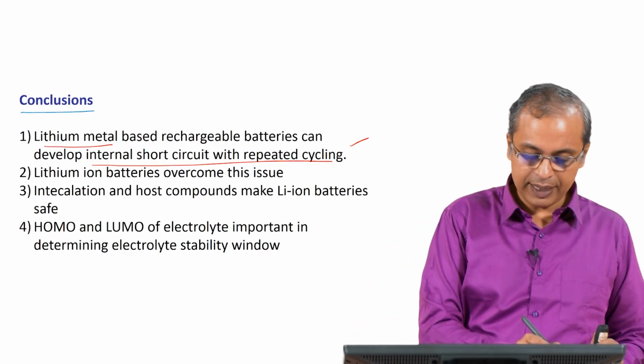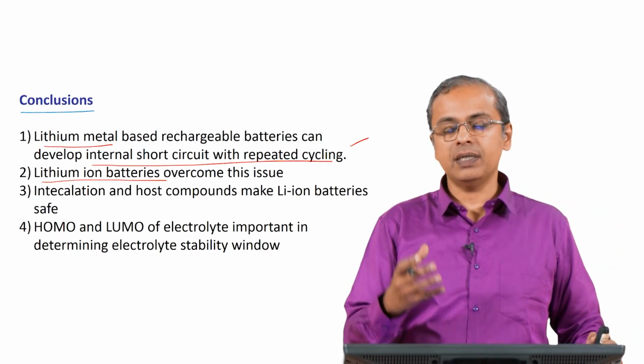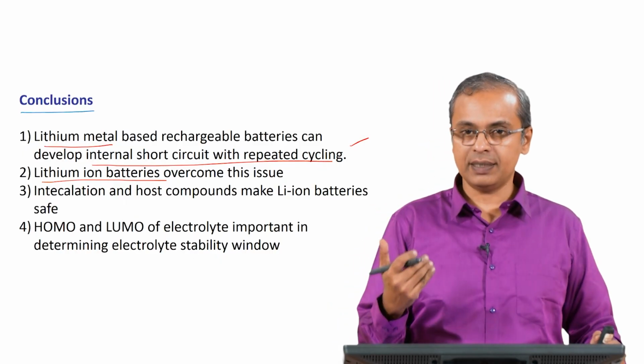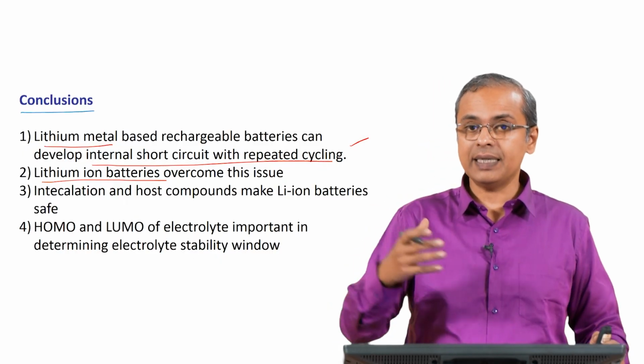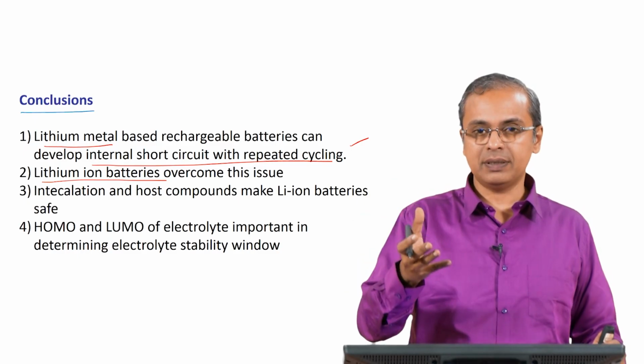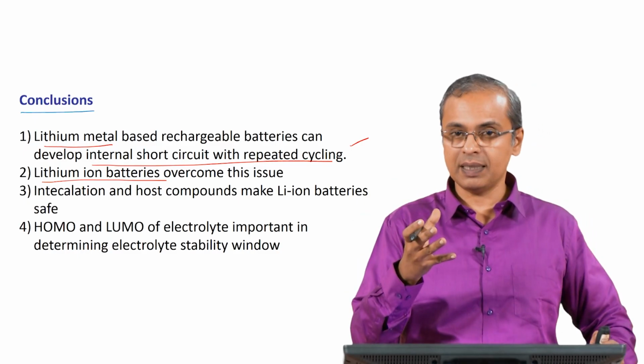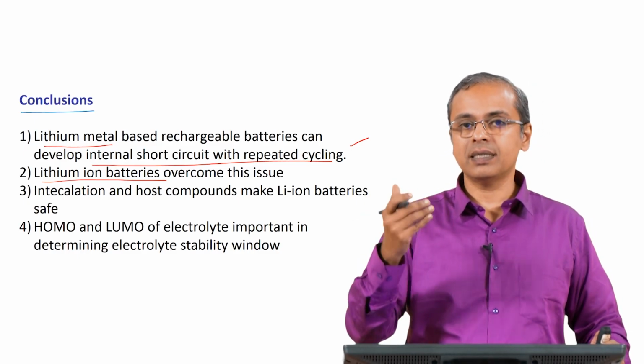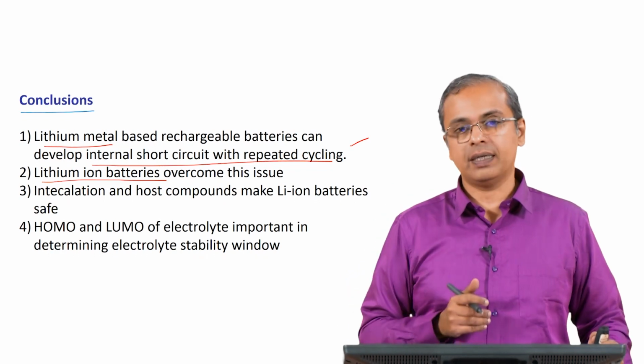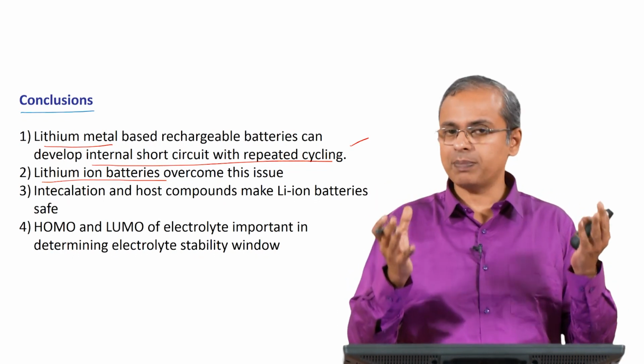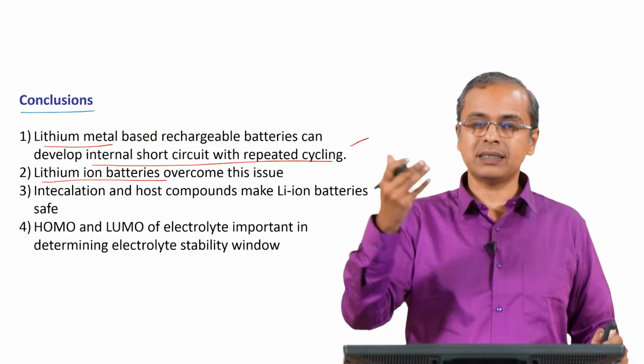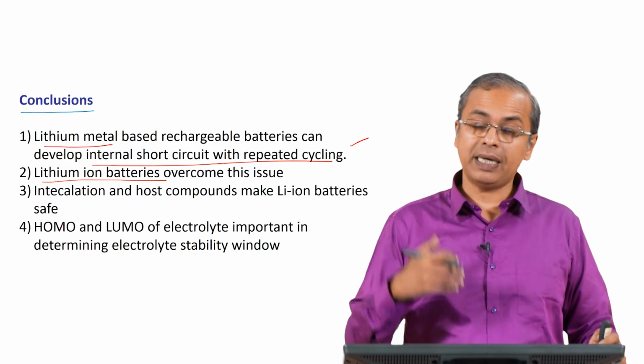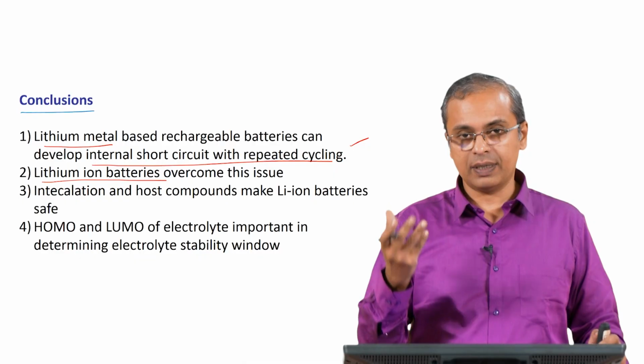The lithium ion based technology creates a situation where metal is not being plated and stripped, and therefore, the dendritic structure, which is the dangerous situation that happens in the lithium metal based system, does not grow in the case of lithium ion batteries. Of course, you have to do some mass balance here to ensure that you are not putting excess lithium into the electrode. If you put excess lithium, then eventually you can have dendritic growth there also.